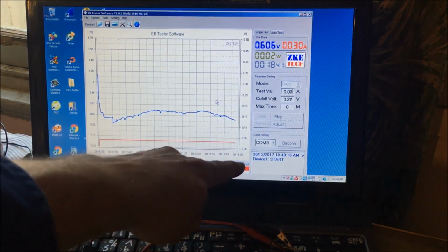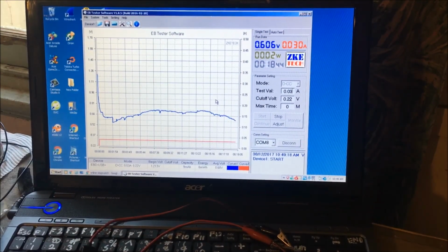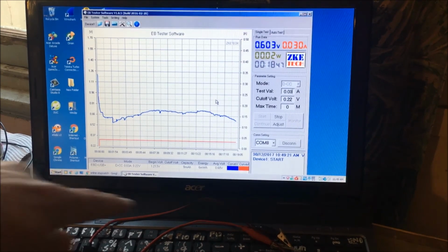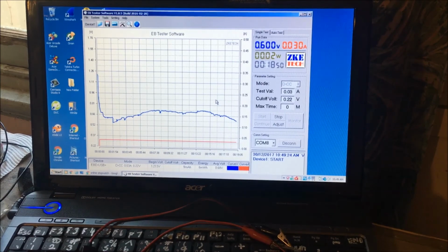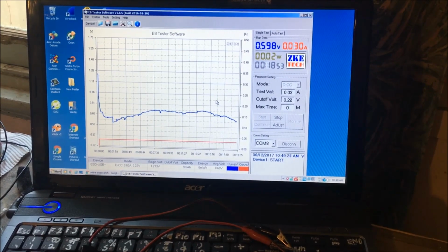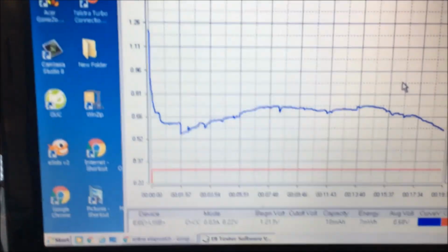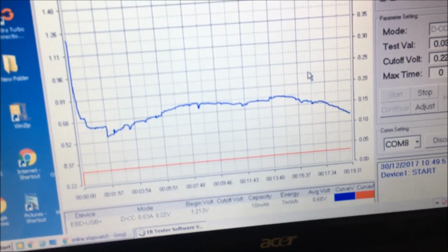But she's dying. For the last 5 charges, we're only getting a half-hour run, which is probably around about 12 milliwatt hours or something, or less. I think it's due to the copper cell electrode. This copper electrode here has had 40 charges on it, and then the other day I thought I'd try 3.5 volts, which seemed to have separated all of the copper out of the cell. If you can see it floating around there, I think it earths out, and that's why we get that voltage drop and that irregular shaped graph.